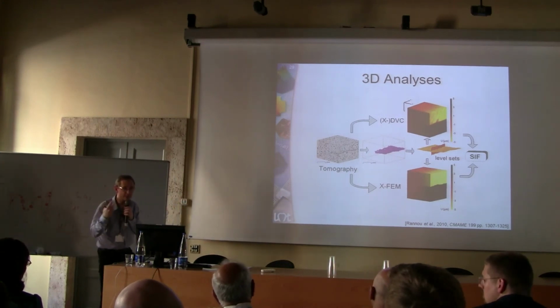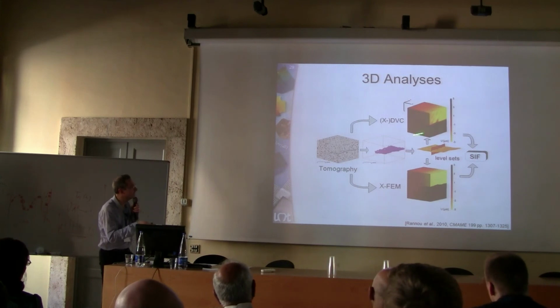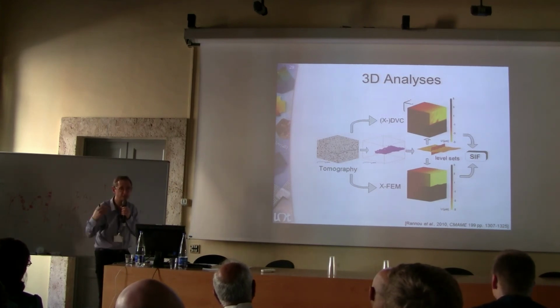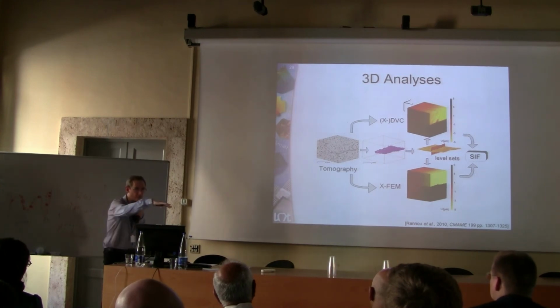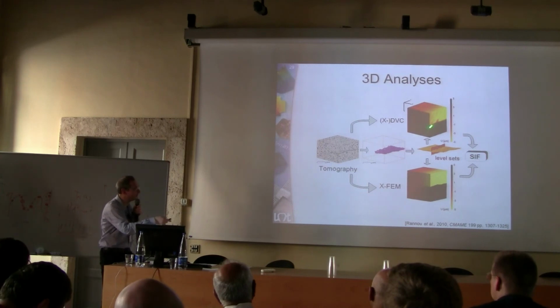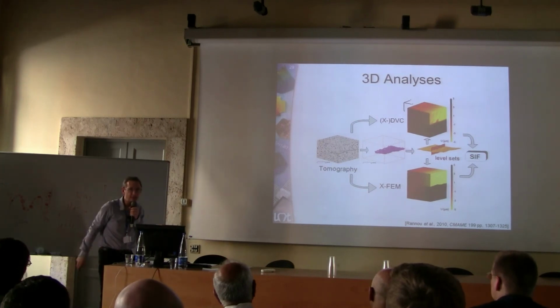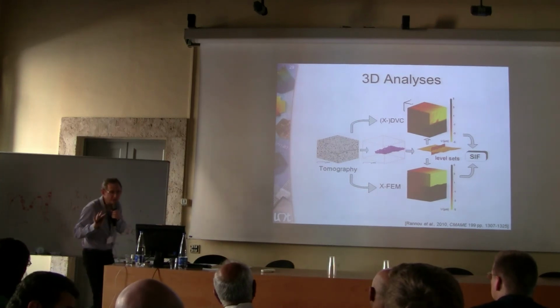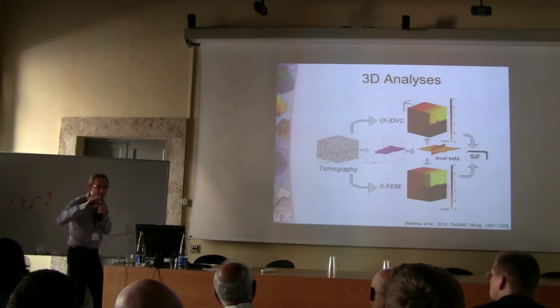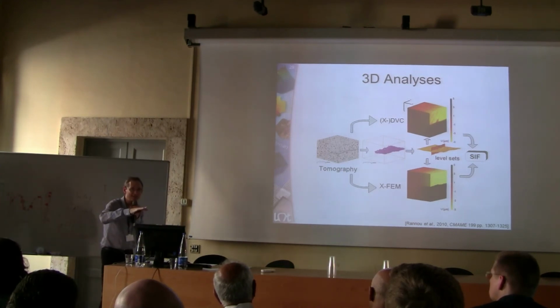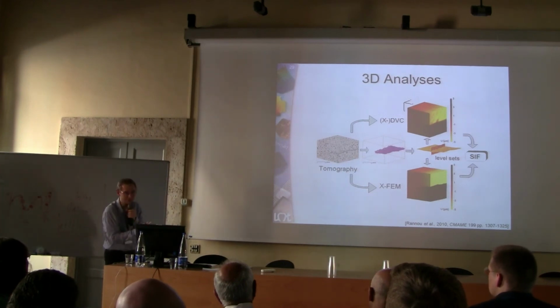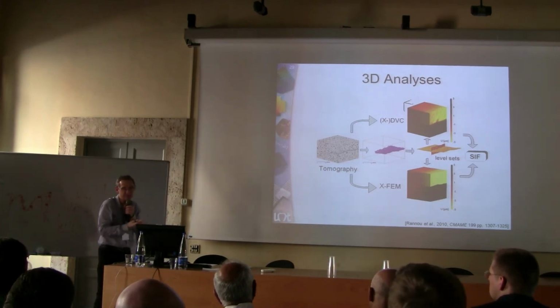Actually what was done here was to develop special extraction techniques to evaluate not only the stress intensity factors but also the crack front location, and use exactly the same technique at the numerical level. That's, to my knowledge, one of the first times where some extraction technique initially developed for experimental analysis was also done numerically. Usually it's obviously the other way around.